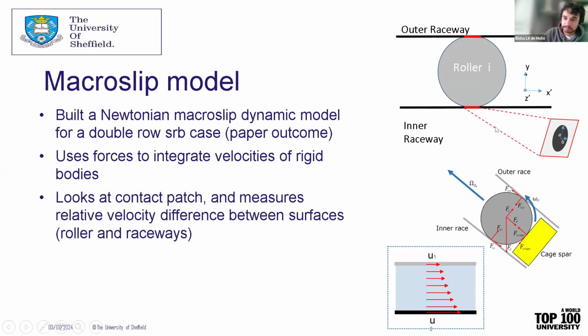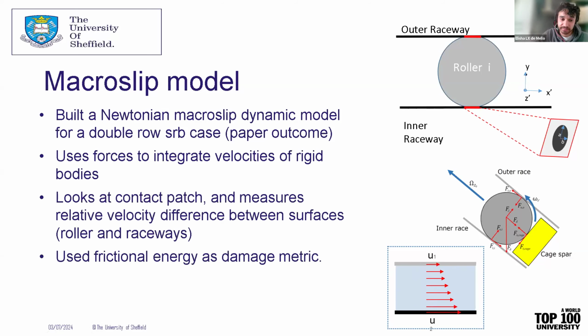And the idea is that a contact patch is formed due to deformation of material. And when the raceway and the rollers move, if the forces are great enough and friction is not sufficient to drive the system, you will get relative differences in the velocities of the raceways and the rollers, creating slip. And this slip is believed to be damaging, and effectively we use frictional energy as a damage metric, that's an integral of slip and traction force in parallel to that direction.